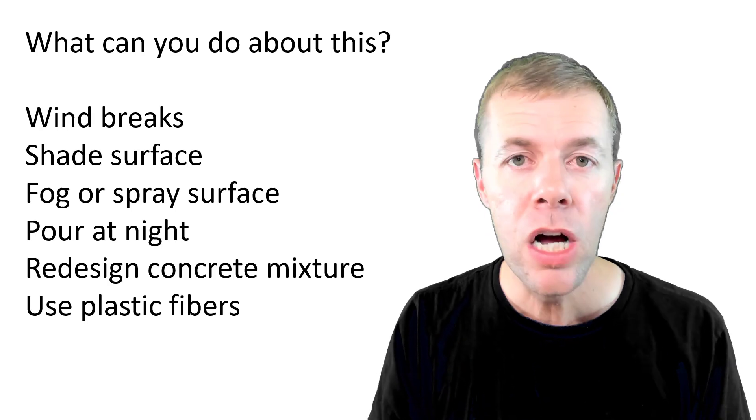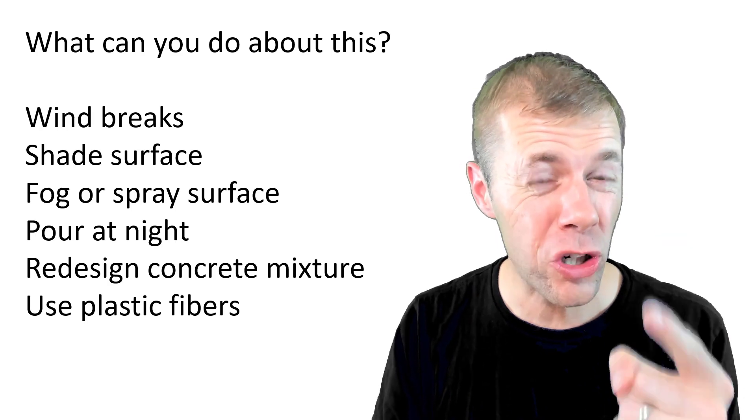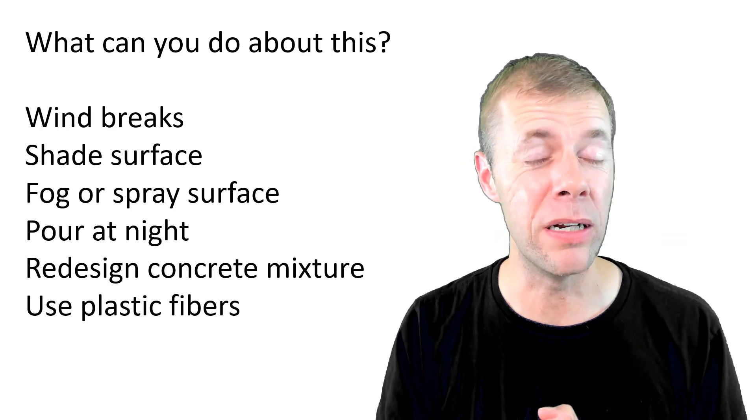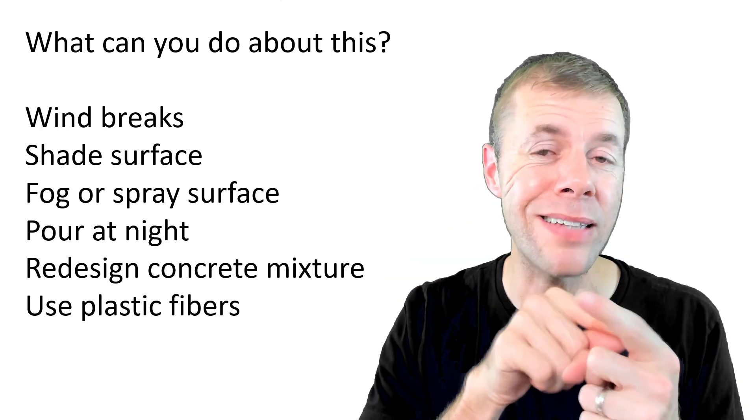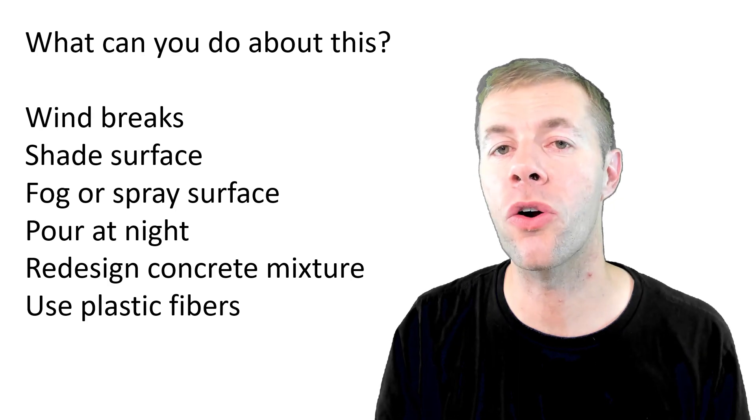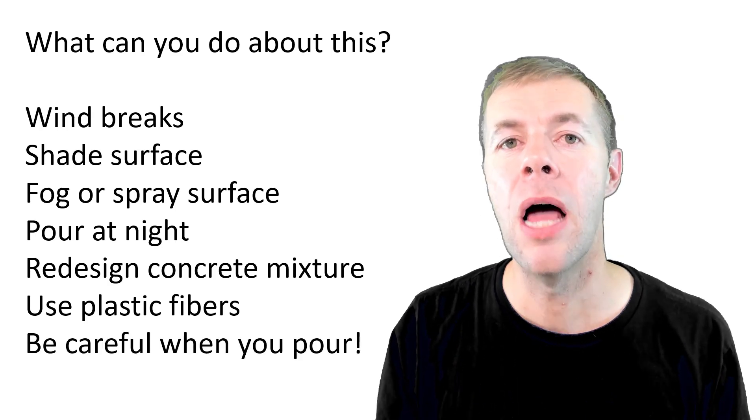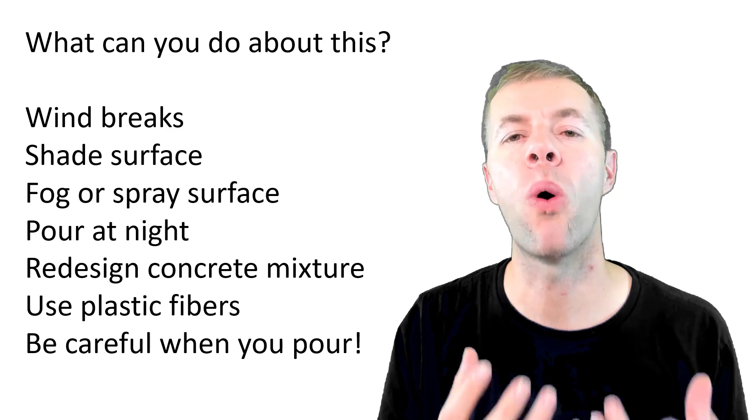Or you can actually use plastic fibers. Now, plastic fibers don't actually hold the concrete together during this time period. Instead, they act like a channel where water can move from the inside to the surface of the concrete once it needs it. And you can be careful when you pour.